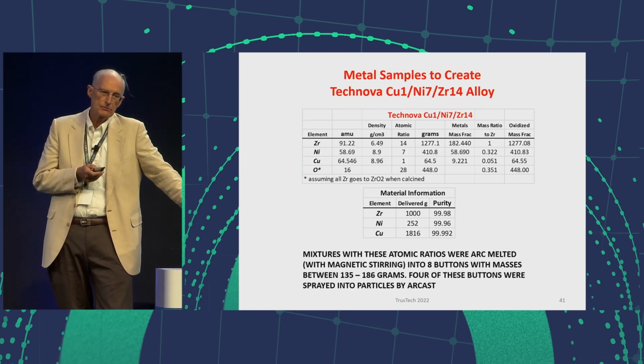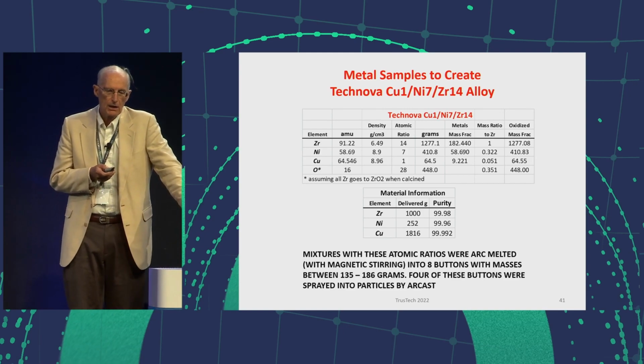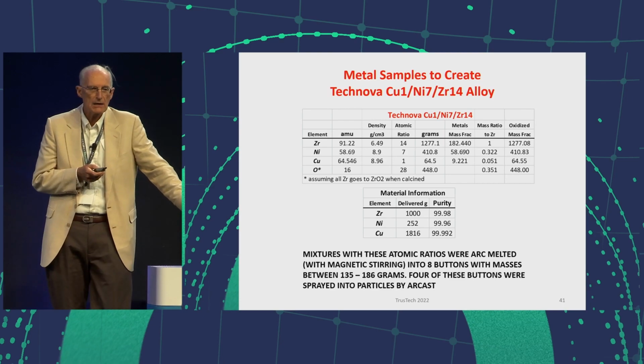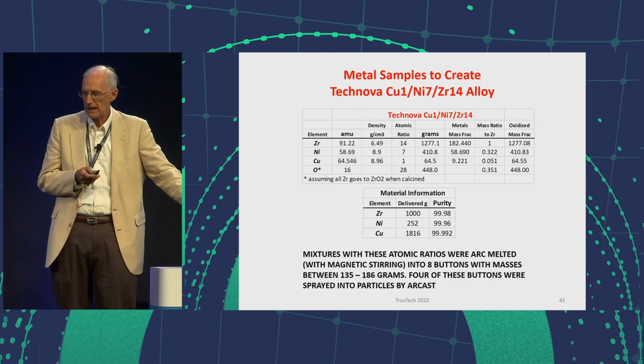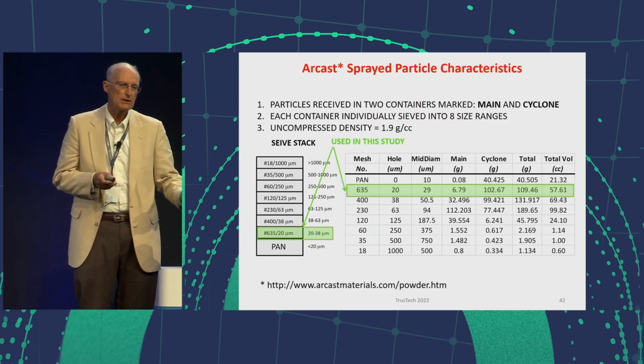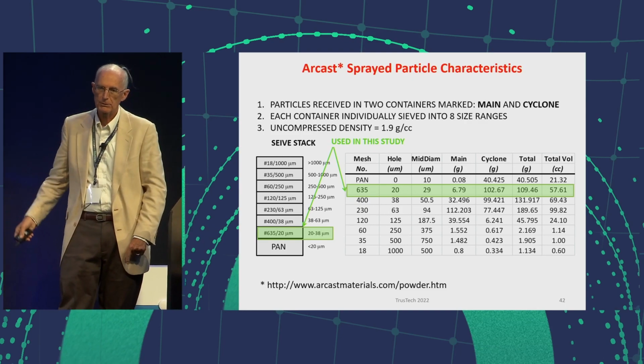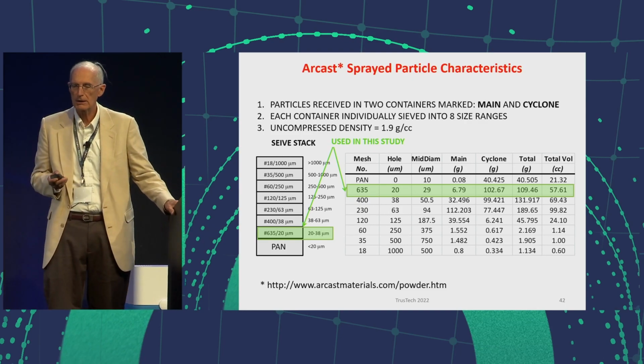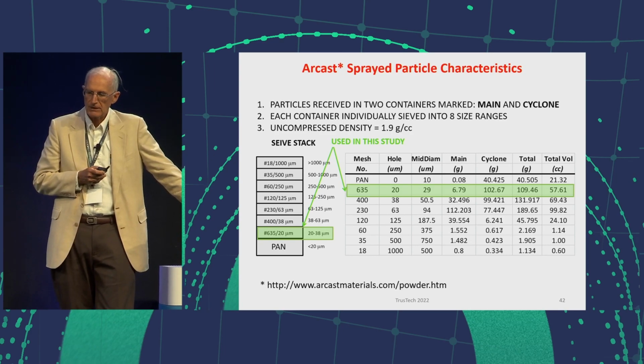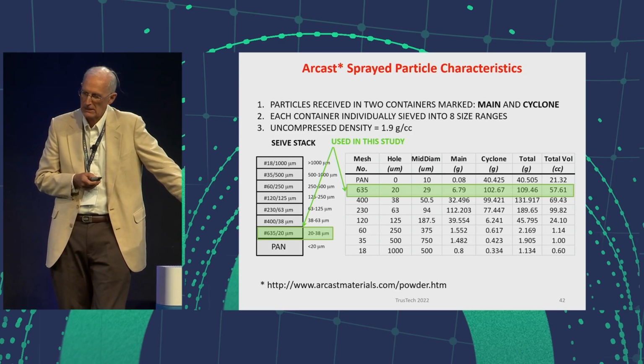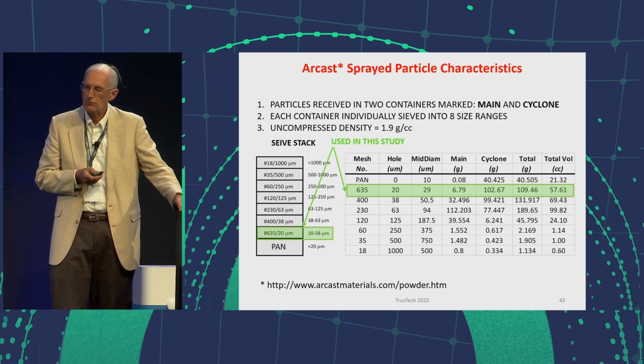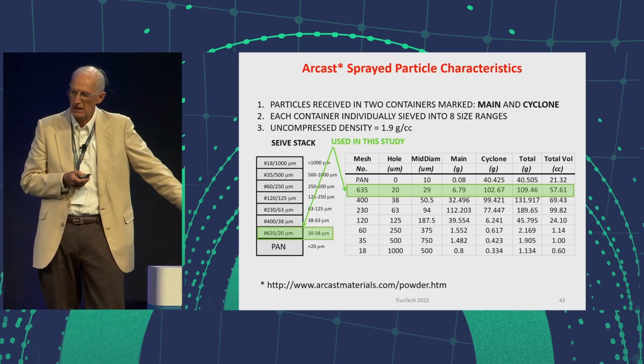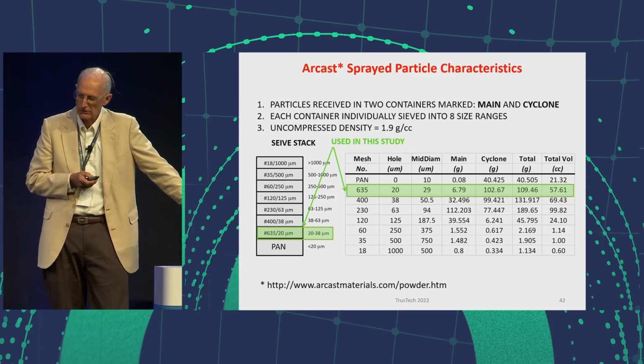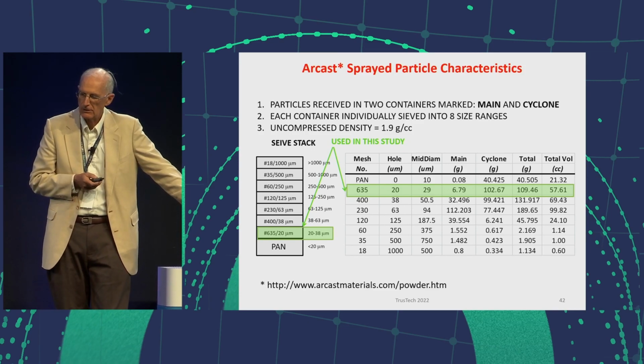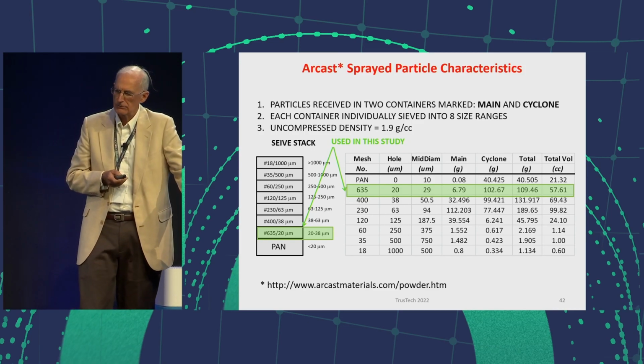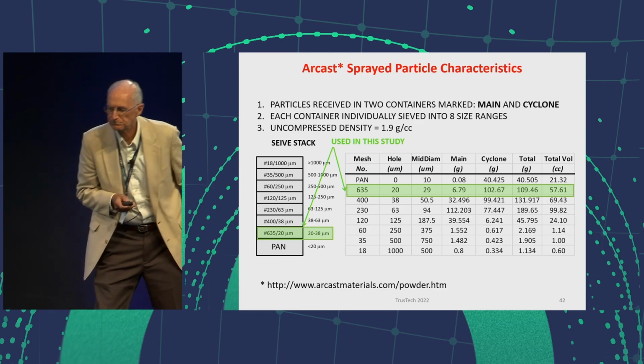Half of these buttons, I used their procedure of spraying these particles into an inert atmosphere. And when you do that, you get a dispersion of beautiful spherical particles. And I sieve these into different particle ranges. The particle range that I used for this one is indicated on this slide, which is particles from 20 to 38 microns in diameter, if I can read that correctly.